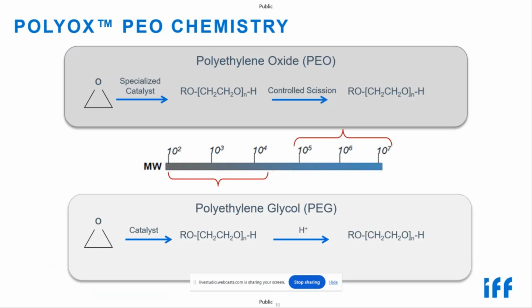Polyethylene oxide is chemically identical to polyethylene glycol, with the difference coming in the molecular weight ranges of each. PEG, or polyethylene glycol, is defined as polymers less than 20,000 Daltons, and PEO are greater than 20,000 Daltons. The chemical synthesis is slightly different, which allows each process to reach the desired molecular weight range for each product line. Polyox uses a proprietary catalyst system to synthesize very long molecular weight chains.